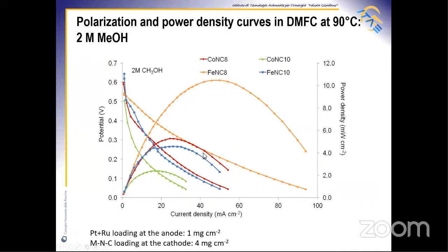For direct methanol fuel cell polarization and power density curves for the various MEAs equipped at the cathode with the synthesized metal nitrogen carbon catalysts, the most performing MEA is the one based on the iron nitrogen carbon treated at 800 degrees centigrade with the 10 milliwatt per square centimeter maximum power density. Certainly, there are other works where higher performances are reported. However, these deal with catalysts prepared by using complex preparation procedures, the use of templates and their removal with aggressive reactants, or high cost precursors.